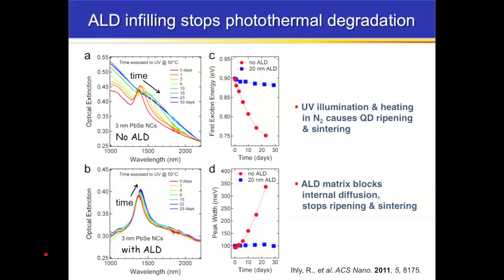The reason that it redshifts is that you get essentially an average size increase in the dots, and the reason that you get a broadening and an eventual total washing out of the feature is because the size distribution gets very, very bad. Essentially what's happening here is the dots are sintering and ripening with these relatively high temperature and UV exposure conditions. We can completely prevent this by using our ALD approach, or almost completely prevent it, I should say.